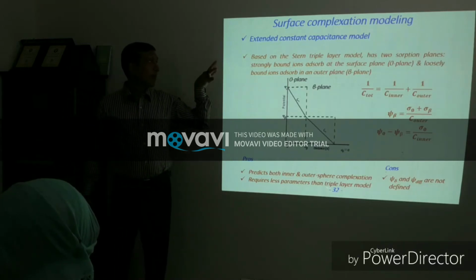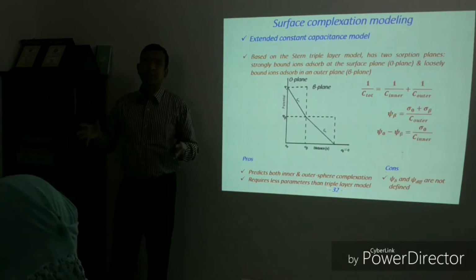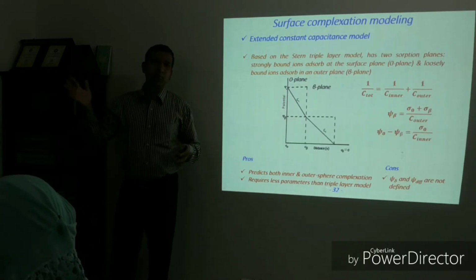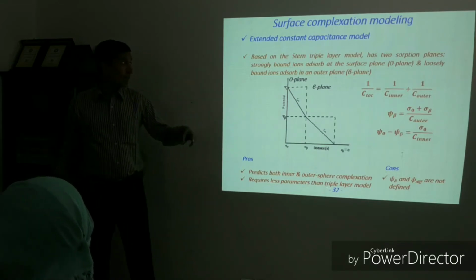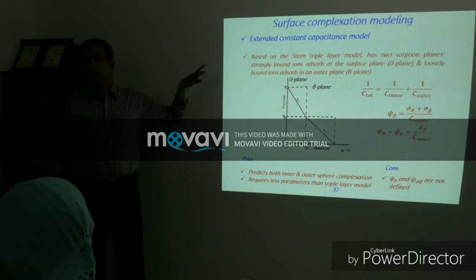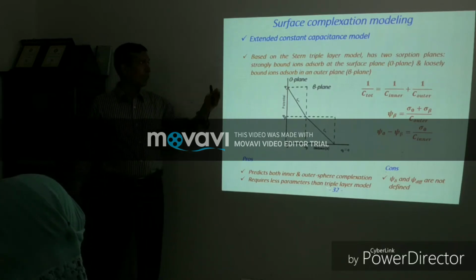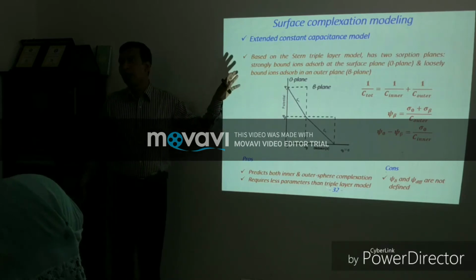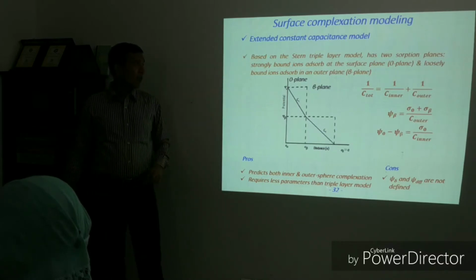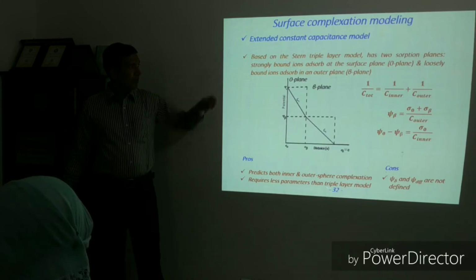So then we have applied surface complexation modeling to understand actually what happens when pollutants are removed from the bulk solution using adsorbents. There are several types of surface complexation modeling, for example, constant capacitance model, extended constant capacitance model, triple layer model. However, we have used the extended constant capacitance model because this is based on the Stern triple layer model.